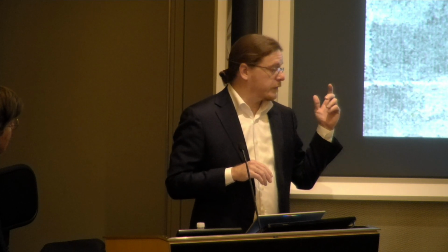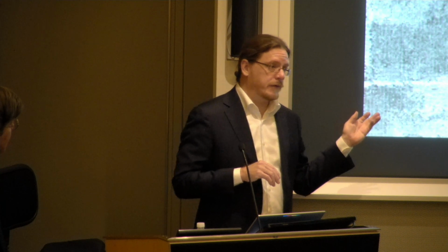So OCT is optical coherence tomography, and it's kind of like sonar with light, essentially. So it is capable of telling us the thickness of all of the translucent layers, so we'll be able to see how many layers of varnish there are on the Night Watch. It's been restored at least 25 times that we know of, and of course, now when we restore a painting, we take off the old varnish and we put on the new, but we know that it's not going to be a single layer of varnish at the moment.